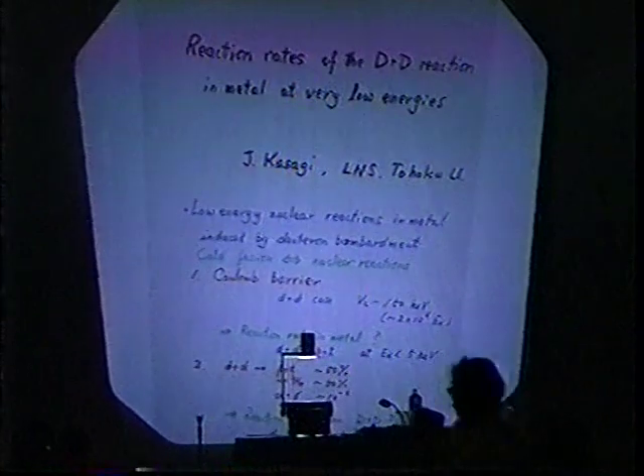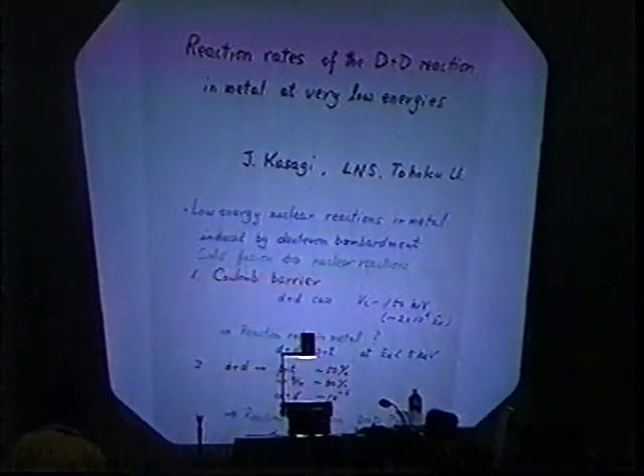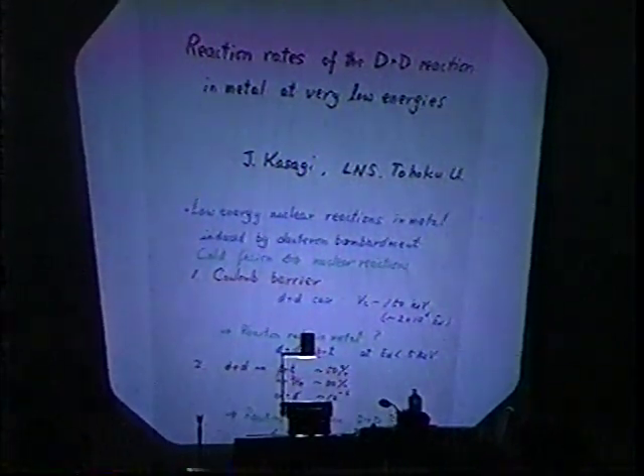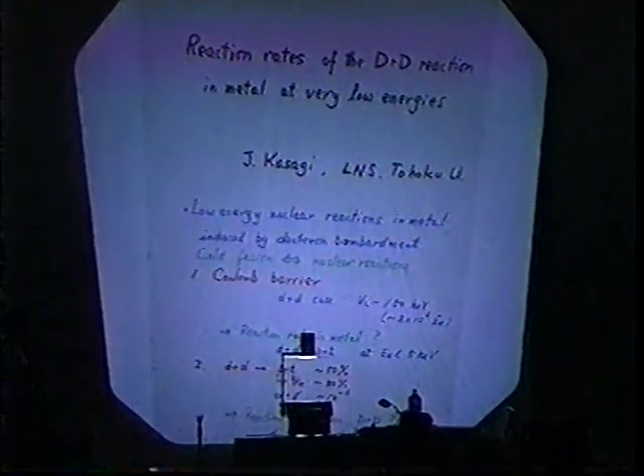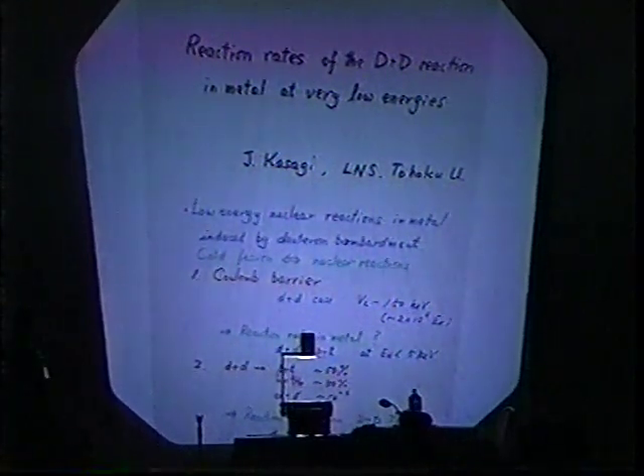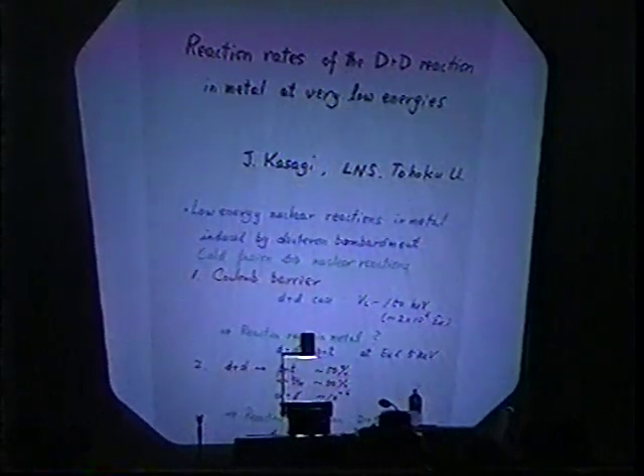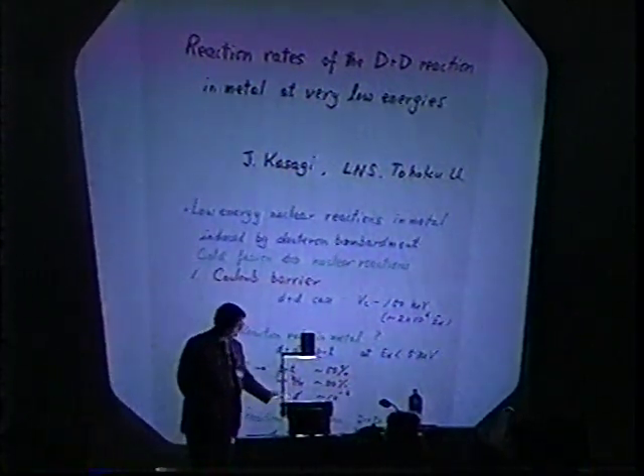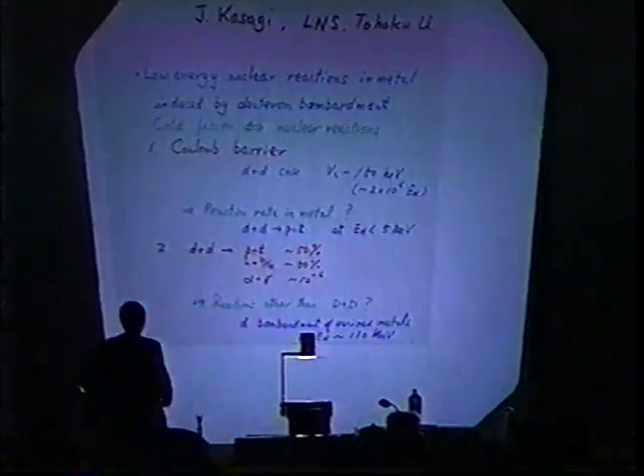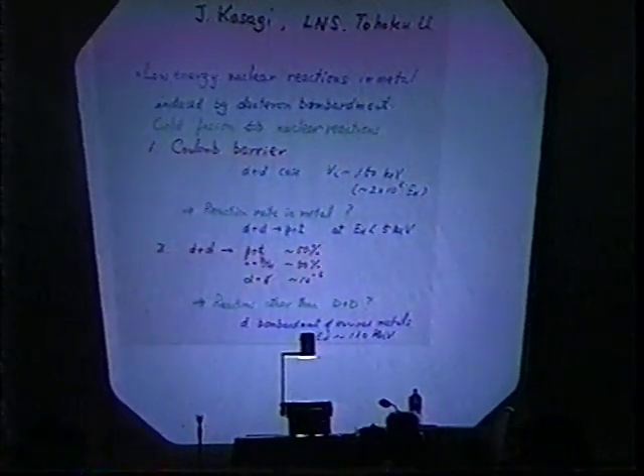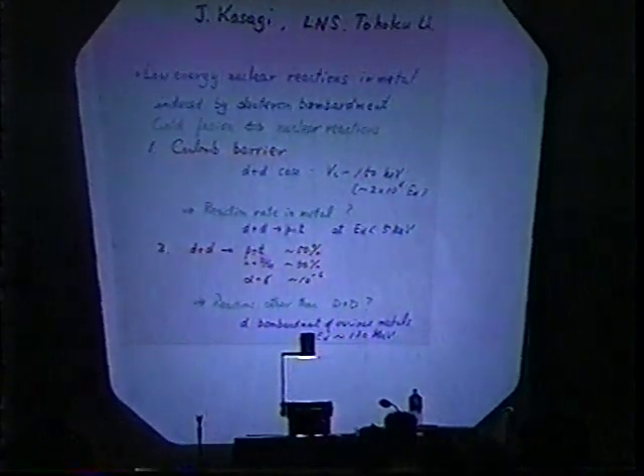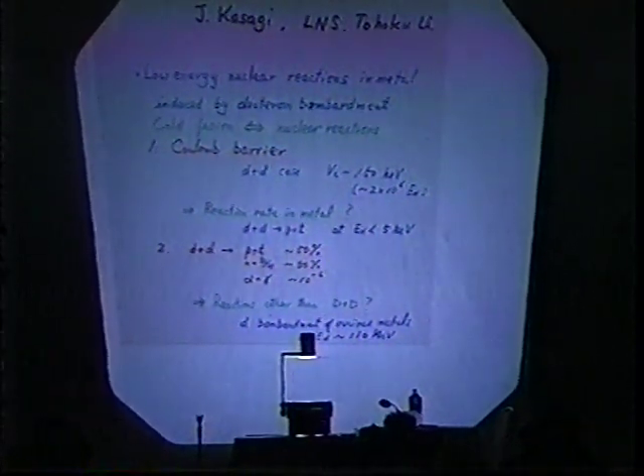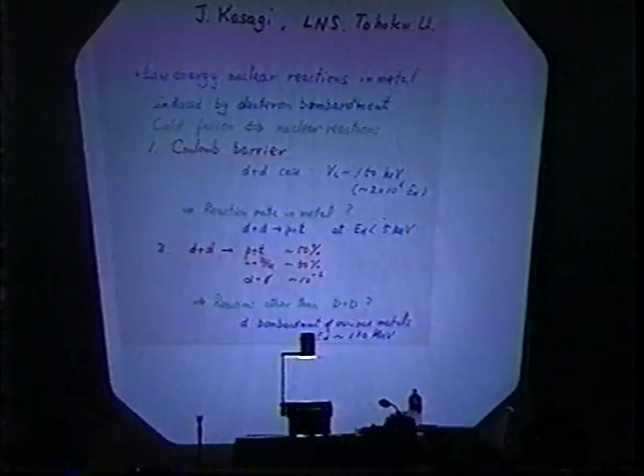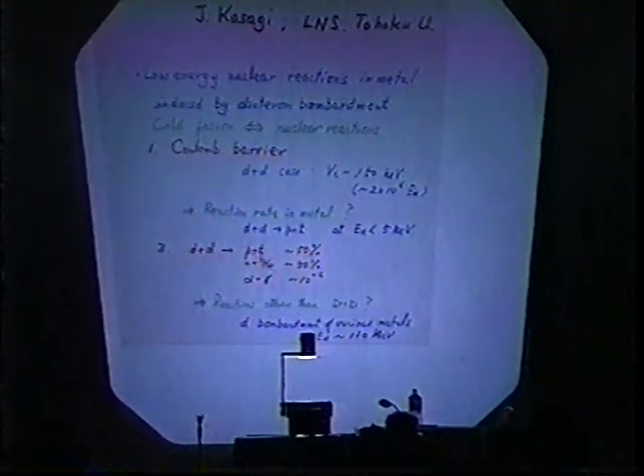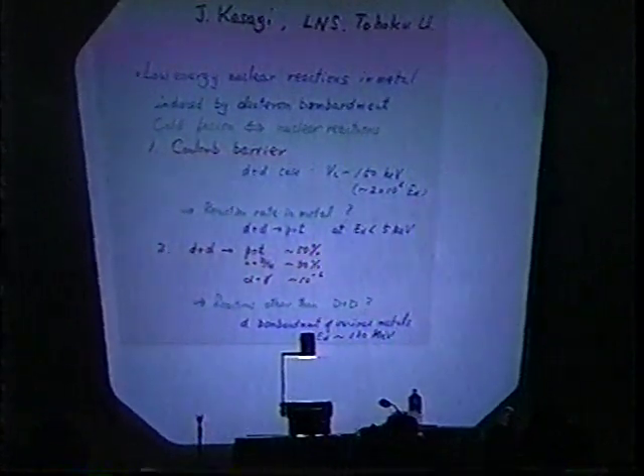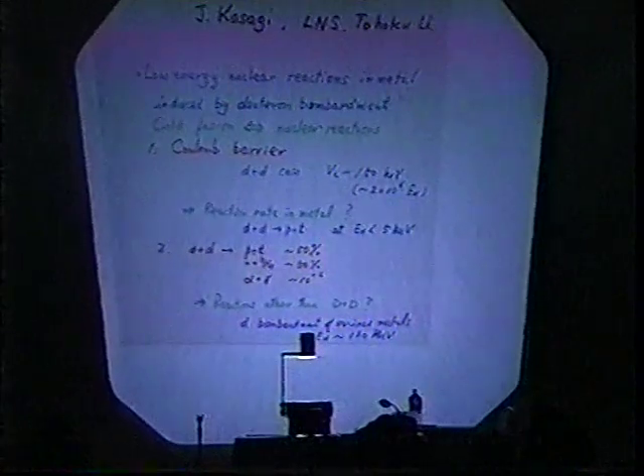For example, if the DD reaction is really happening in the metal, the height of the Coulomb barrier is something around 150 keV. It's something like 10 to the 6th times the thermal energy of neutron. And also, as discussed from the beginning of this cold fusion business, there is a big difference between usual reactions of D plus D, because 50% goes to the P plus T channel, and another 50% goes to the N plus helium-3 channel. And even if we consider the alpha channels, it's negligibly small.